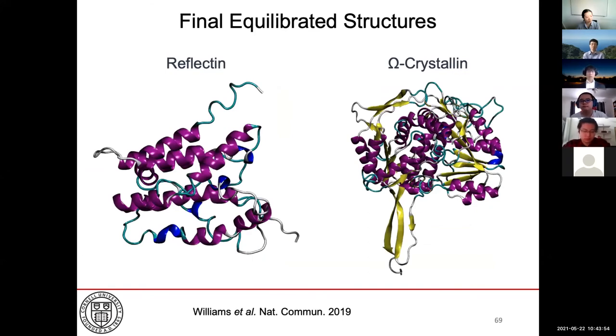And here are some of the structures for reflectin and crystallin. Basically what we found is that the reflectin monomer has a very large number of random linker regions, as shown by these strands over here. And this suggests that the structures are very flexible. In contrast, crystallin over here is highly globular, and therefore it is likely to be structurally rigid. And because of this rigidity, we imagine that crystallin will have suitable pockets for pigment molecules to bind, which may explain why crystallin exists exclusively in the pigment granules.